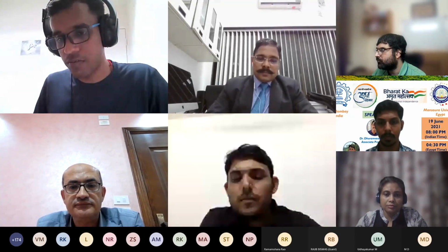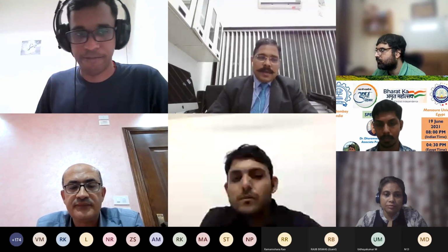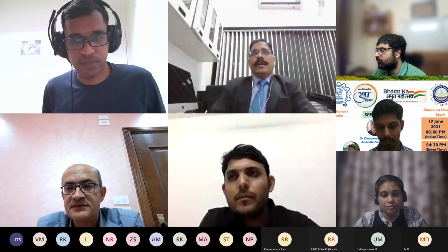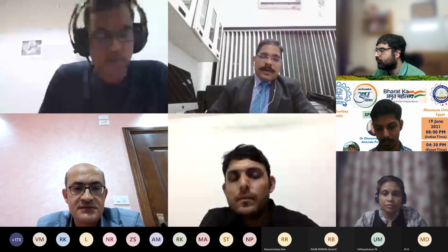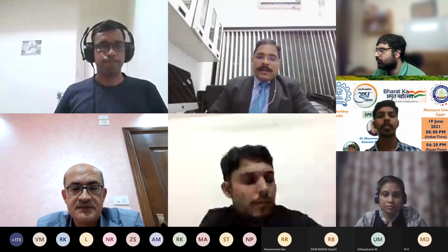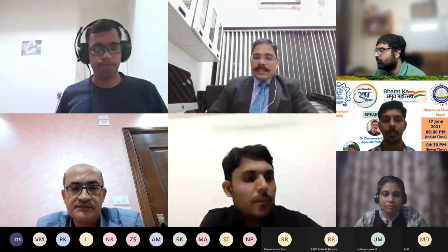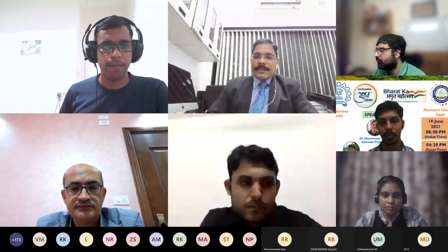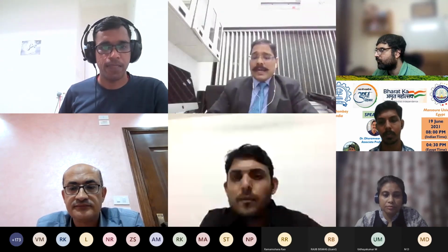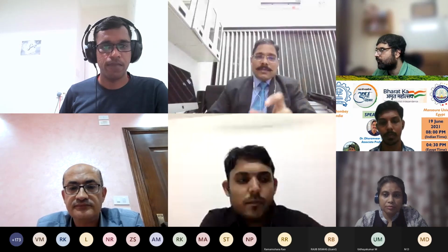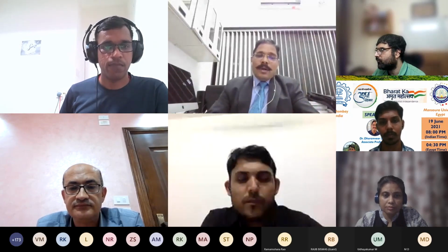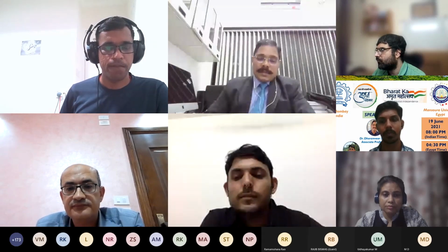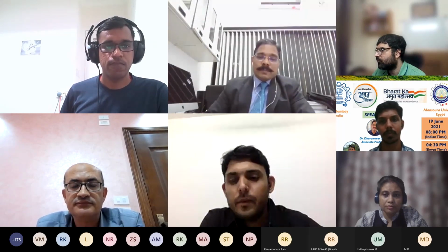So, Dr. Singh, would you like to add? Yeah, you are right actually, Prabir. And also, if you see IRC 37 2018, it clearly says that if you are going to use VG40, the minimum viscosity has to be 3600. That is a very, very clear instruction that has been given. But you rightly said, we should not only look into the viscosity for classification, but other properties also we need to look into. We need to pay equal attention to that.